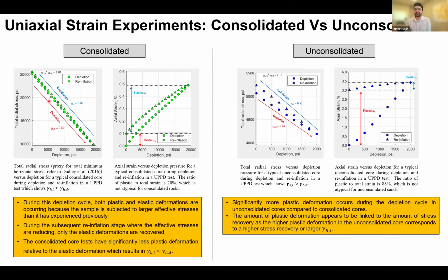So the stress change for a consolidated sample during depletion and reinflation is basically overlapping, and so the ratio of the injection to depletion coefficient is actually quite close to 1.01 in this case. Also very interesting to see on the strain side of things. If you look at strain versus depletion, this is depletion, this is reinflation. What we saw in consolidated samples was that most of the strain was elastic and was recovered during injection.